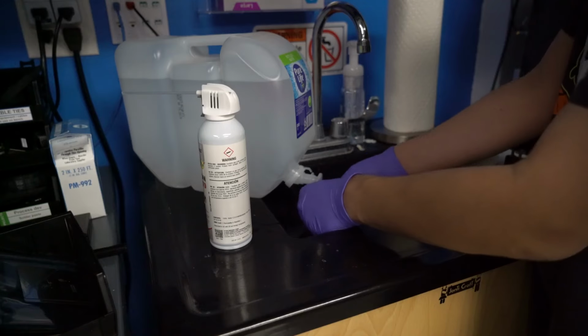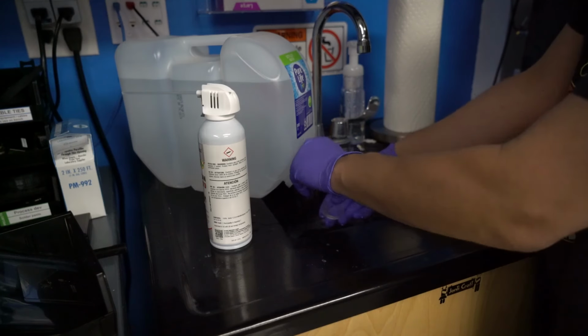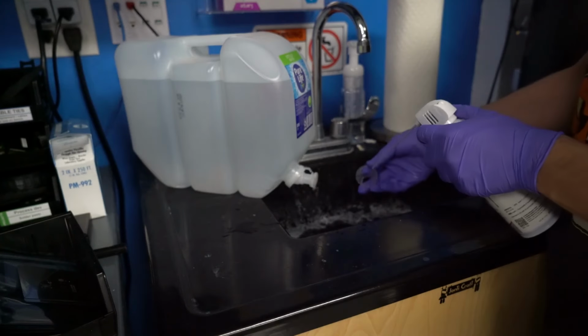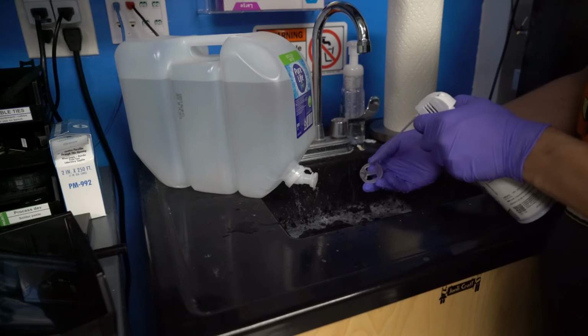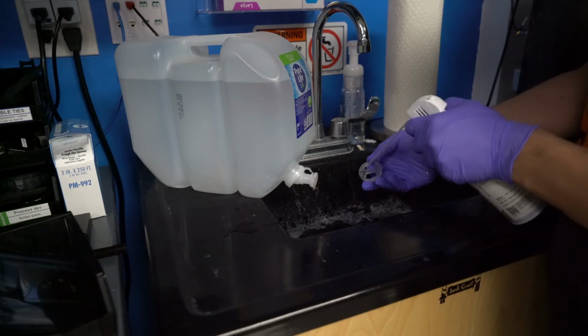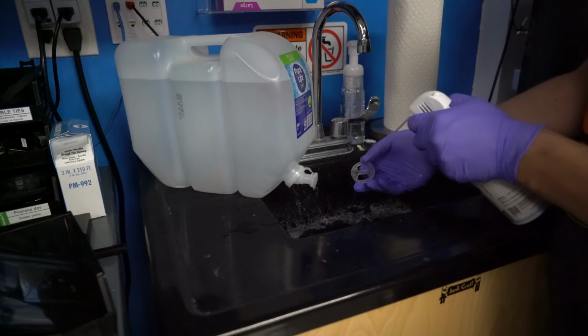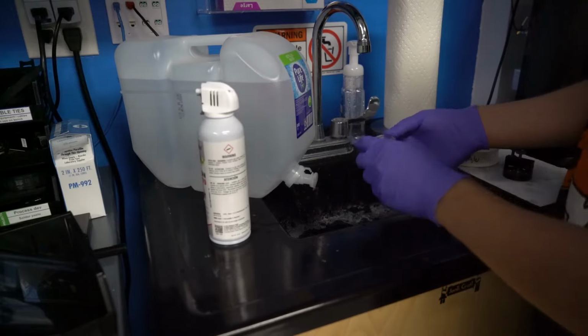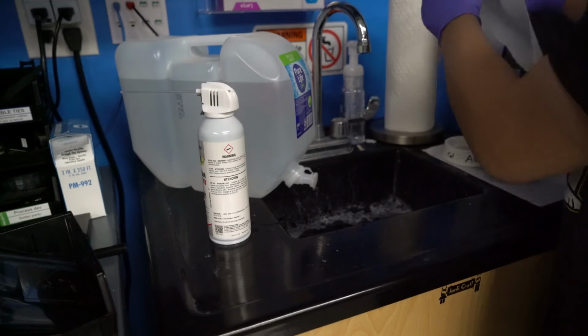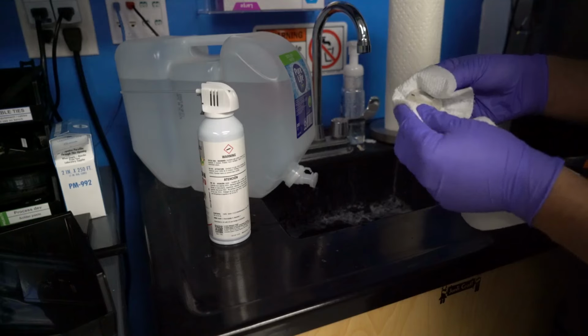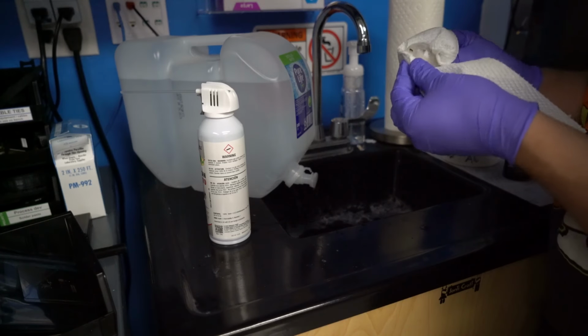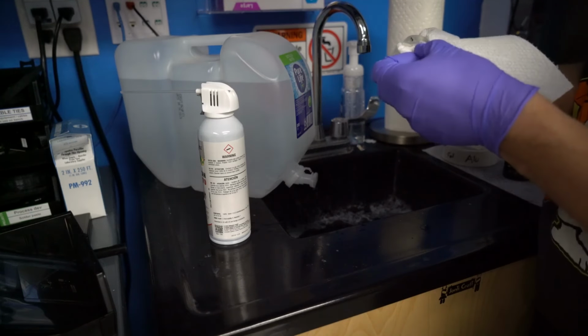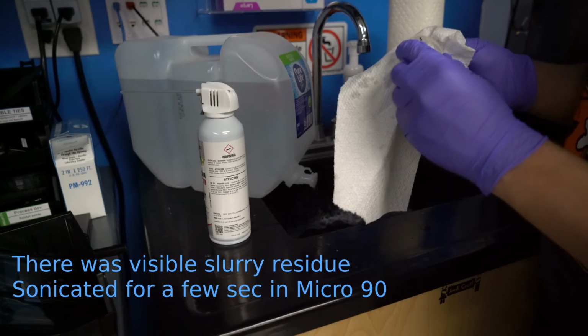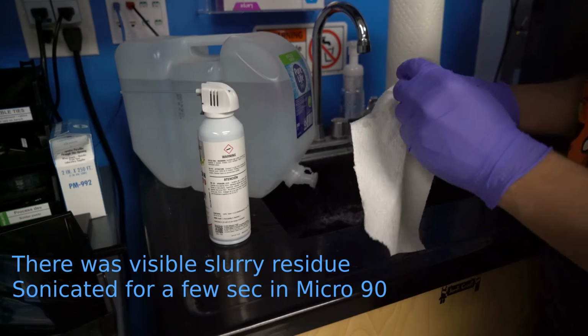Definitely distilled water here. We don't want to use tap water to avoid getting any sort of mineral deposit, especially around here. My tap water is pretty hard. And then blow all of the water off of the top surface. We don't want to be touching the surface that we're imaging with anything now that we have this extremely high quality finish. And we're going to take a look at this. I'm probably going to sonicate it, but I'll take a quick look under the microscope just to see if that's necessary.